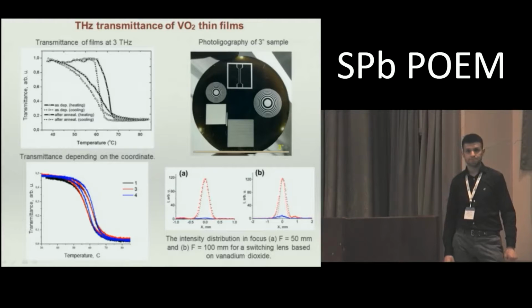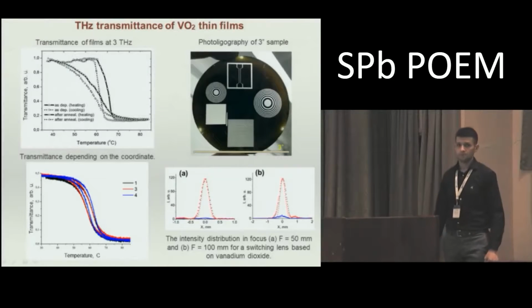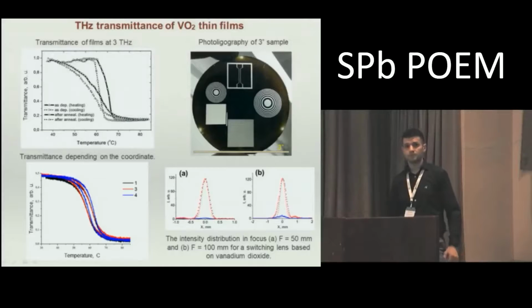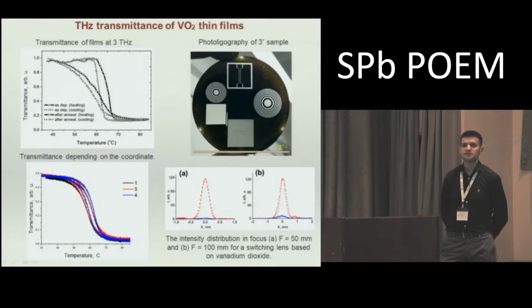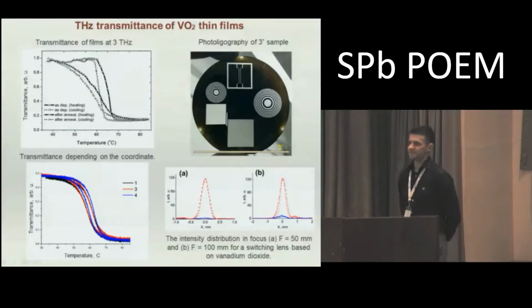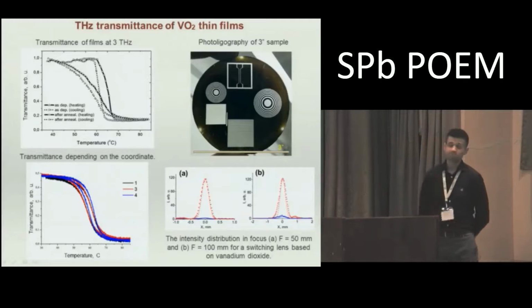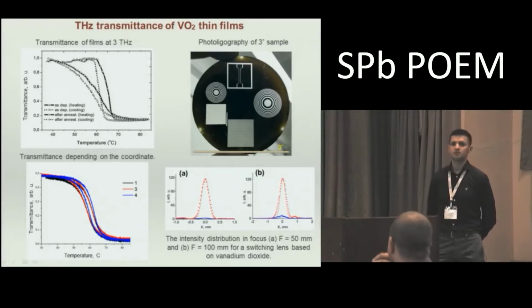Yes, please. May I ask a practical question? This switch, did you see any degradation in number of cycles? For the films, it's about 1 million cycles, I think. Of course, it depends on the thickness of the film. The thicker the film, the fewer cycles I think we will get. And what is the switching time? It's a really good question because we did not make such measurements, and we will do it in the close future.